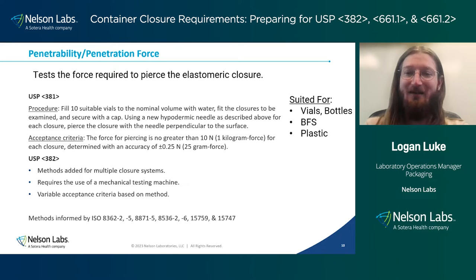It's not stated as part of the acceptance criteria, but it does give guidance to check for the fact that if you go to pierce the vial and the rubber stopper, if we're talking about vials, just plops straight out of your cap, it's not going to pass. It's not a good seal on there if the force required to puncture it is pushing your septum out of the cap.